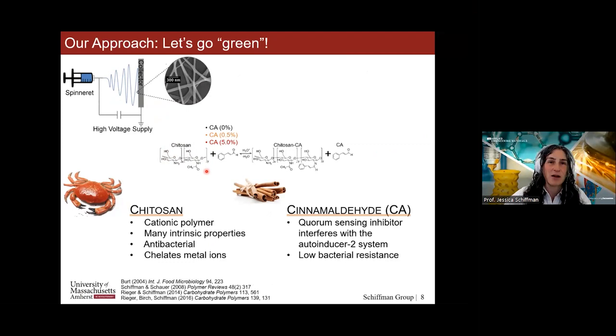And chitosan has many intrinsic properties from that amine group. It's antibacterial and it holds on to metal ions. You know, that's what the chelate means. It can hold on and help for remediation, such as water remediation. We also took advantage of this amine group to do a Schiff base reaction to attach some cinnamaldehyde to the backbone, as shown here. And actually, it was pH reversible. So when we were in a wound setting at an acidic condition, we actually released that cinnamaldehyde.